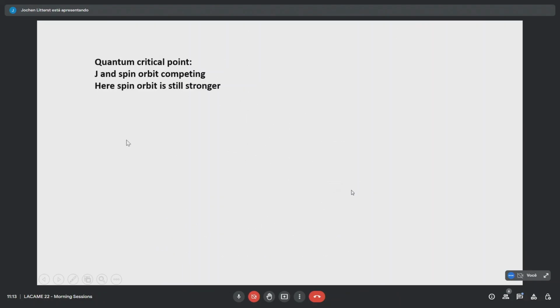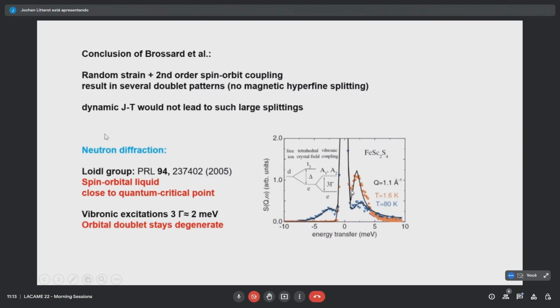His conclusion was that this comes from random strain, which comes in by second-order spin-orbit coupling. And his interpretation was that there's no magnetic hyperfine splitting, but several doublet patterns. But he was wondering, since the quadrupole splitting was far too big and he could not really relate it somehow to the Jahn-Teller effect.